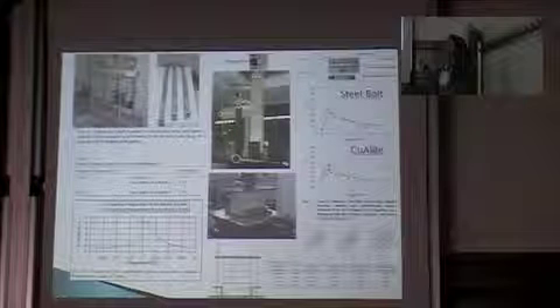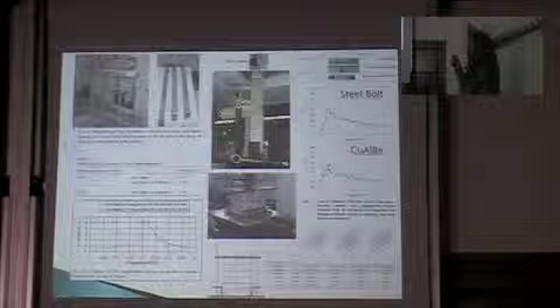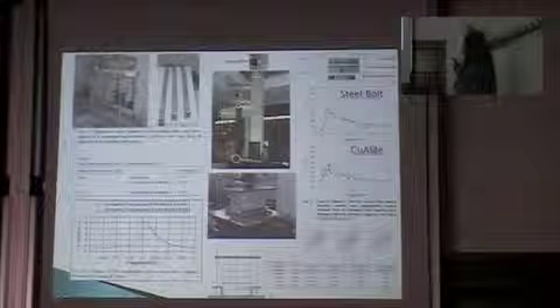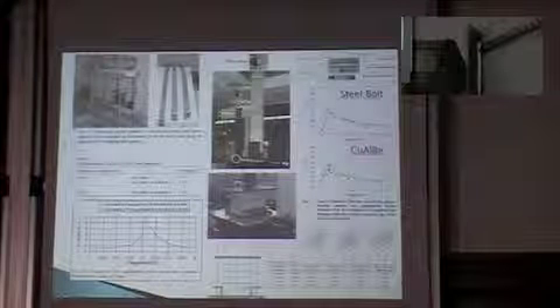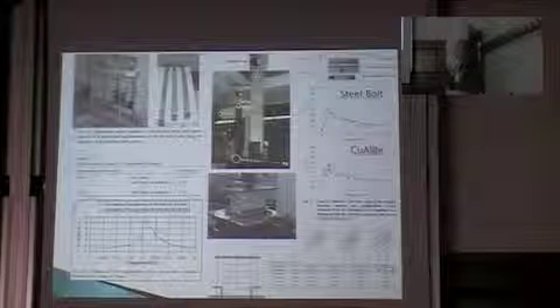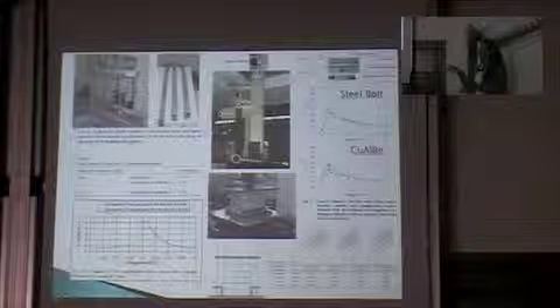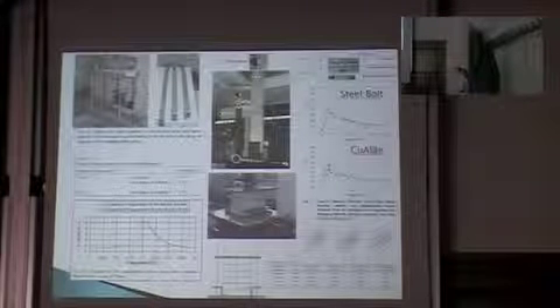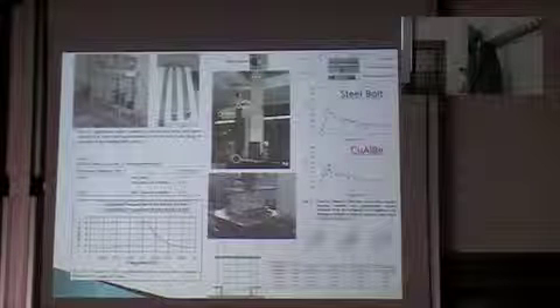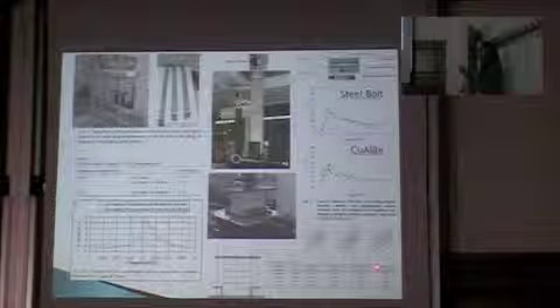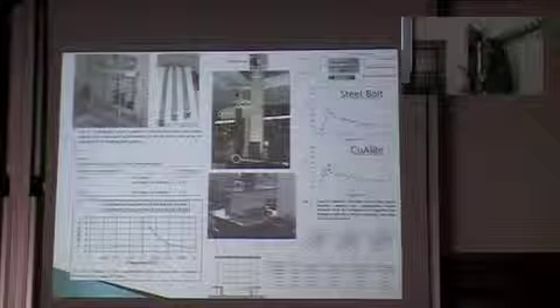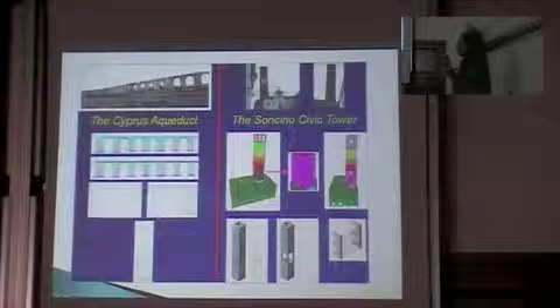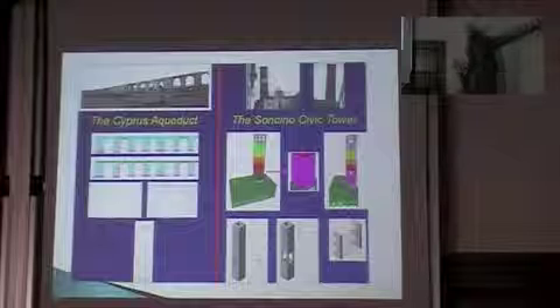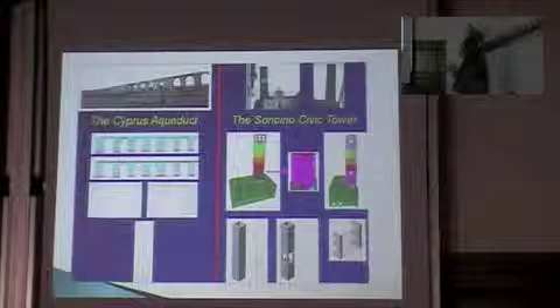Why? Because we want to understand how we can model the structure, including the shape memory alloy device, without changing the dynamic response of the structure, by actually representing the experimental results. So how do we obtain, for example, the same frequencies and the same maximum displacement that we obtain from our shaking table test? This is a preliminary study for designing our retrofit intervention on monuments, because in this way, once we establish how to model numerically our devices, we can design how many devices we need and where they need to be located without having to run too expensive analysis.